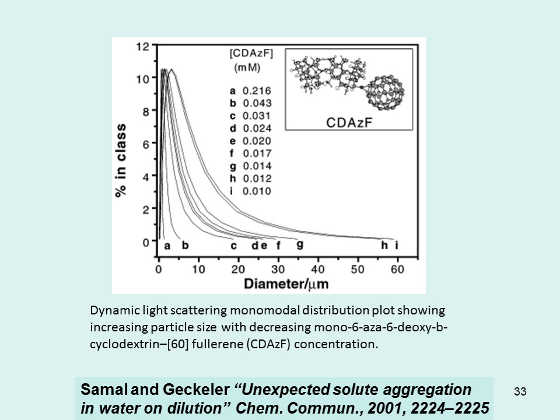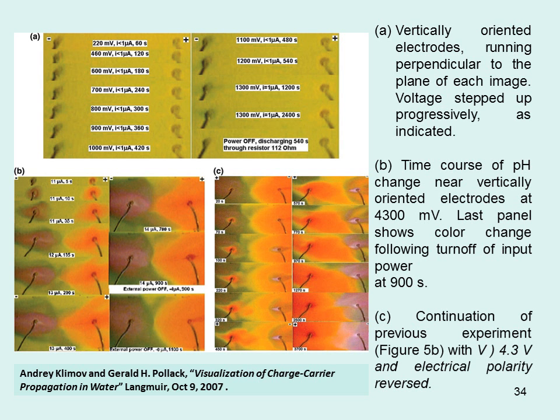Now, two other lines of evidence. This is Samal and Geckeler's paper from about 5-6 years ago, where they essentially showed that the distribution of a solute was totally irregular in a water solution, and that they got this clustering, where in very dilute solutions small areas seem to form where the concentration is high compared to the rest. Inhomogeneity in dilute solutions.